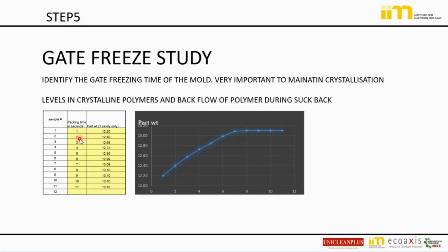Second, if I give 2 seconds, obviously the weight will increase. So I will give 3 seconds, 4 seconds. I keep on increasing by 1 second or 0.5, depending on the part. Then after some time you can see a flat area here. After 7 seconds, the weight is 13.09, 8 seconds 13.10, 9 seconds 13.10, 10 also 13.10, and here the weight is not getting affected by increasing the holding time. It means my gate is frozen.